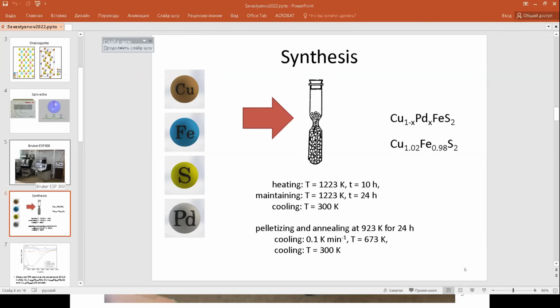The ampoules were heated up to 1223 Kelvin over 10 hours, maintained at this temperature for 24 hours, and then slowly cooled to room temperature. The resulting ingot was then ground under acetone, pelletized, and annealed at 923 Kelvin for 24 hours. Then it was slowly cooled down to 673 Kelvin and then cooled to room temperature by switching off the furnace.